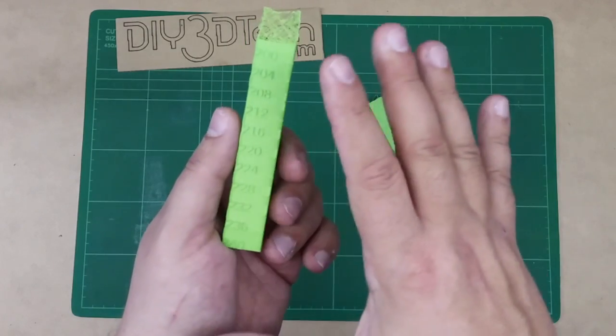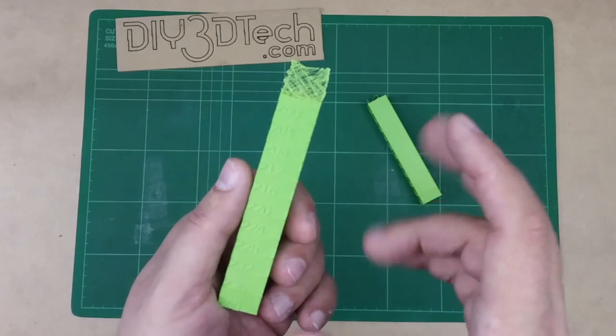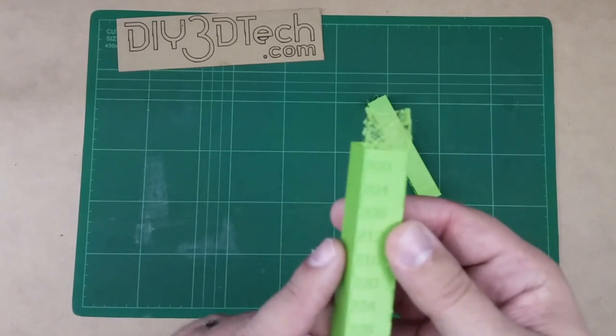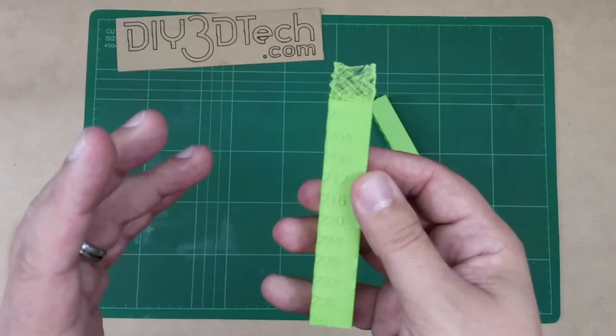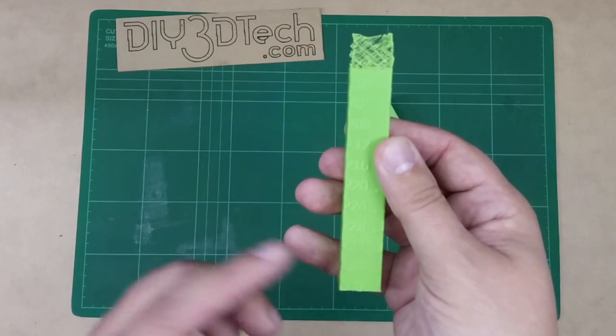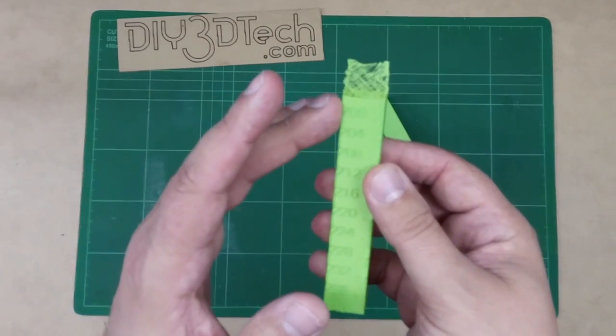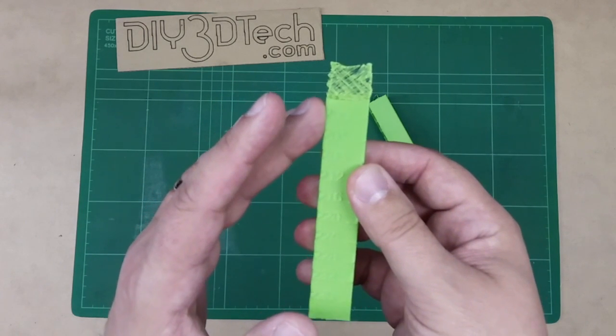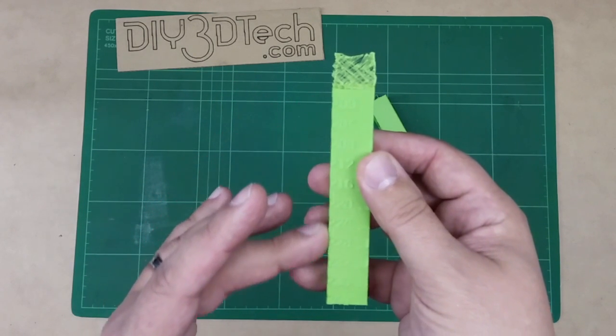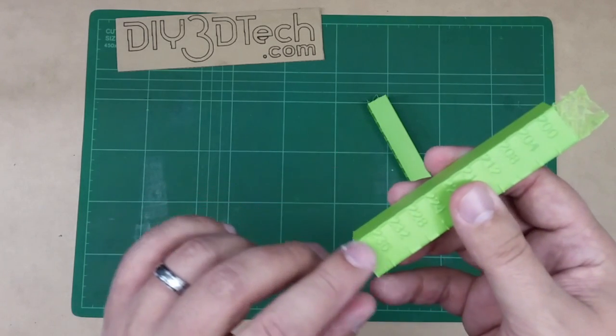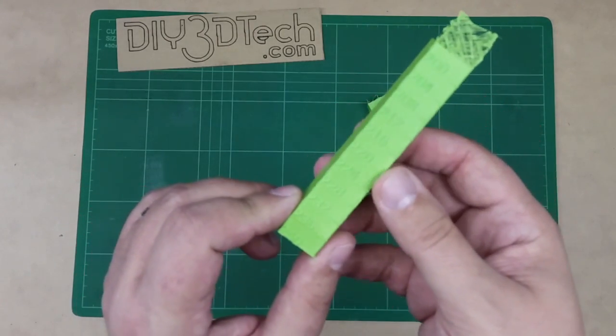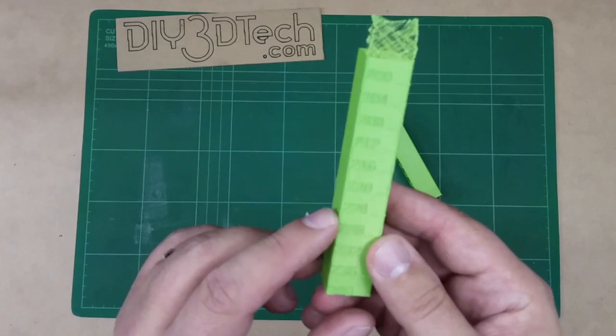Now, I do think this is a little bit machine specific because there are certain quirks in each machine's temperature consistency and things like that. So I did this on the Monoprice Mini, Monoprice Select Mini. And this is the Rigid Ink PLA plus. So now it says that you should print between about 230 and 240. And as you can see here, I went all the way down from approximately 200, which was too cold, all the way up to 240, which 240 was a bit too warm because I did get a lot of compression in the layers there.